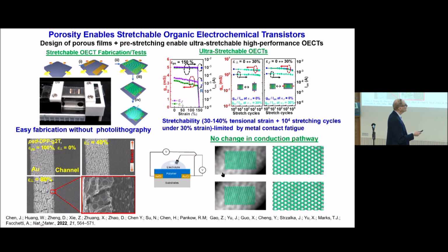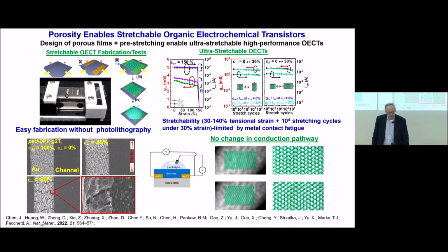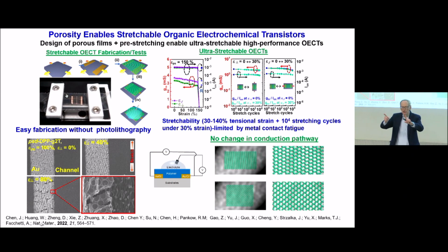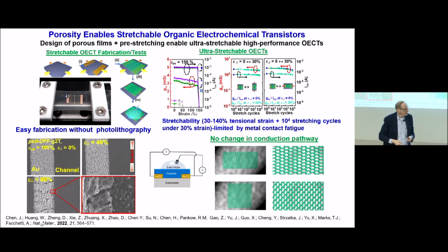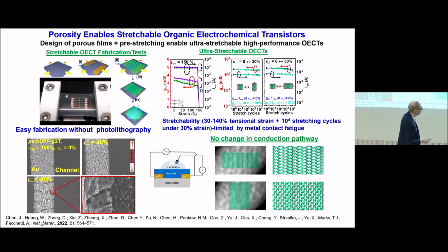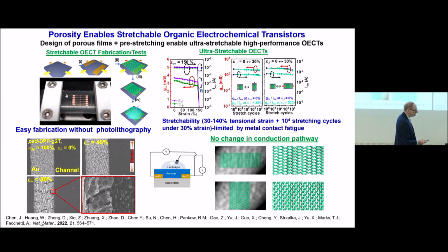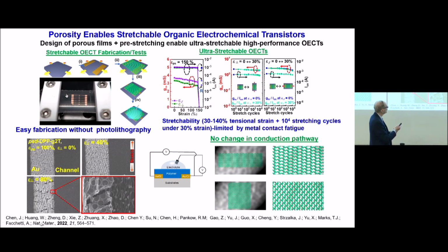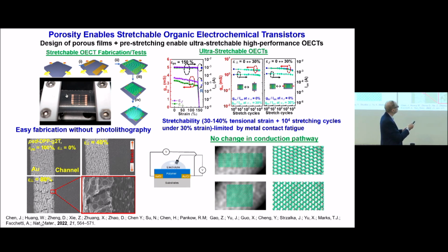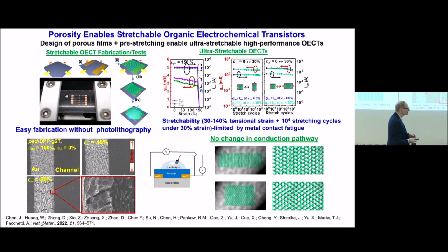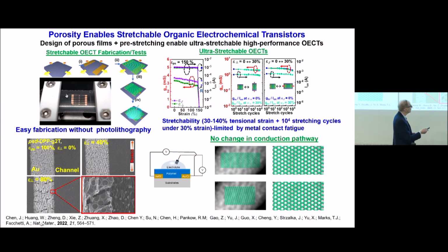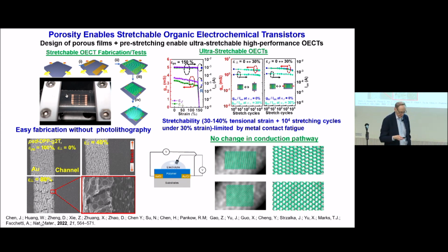So this is a machine we have to do the stretching and measure the mobility. And so you can see we can. But you can see here's the transconductance with strain of one of these materials, and it changes very, very little. And here's just showing, so you might say, yeah, well, it did it once and then it'll die. But no, here we have number of cycles up to thousands, and you can see very, very uniform mobility. So these have the mobility that you want with the transistor, and yet they can stretch.